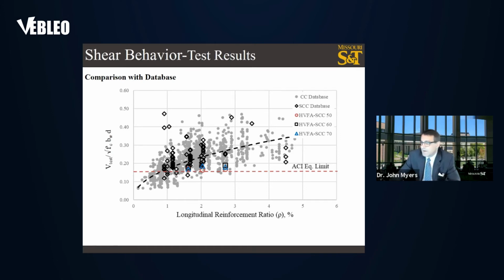Here you can see the experimental data of the different high volume fly ash values, other SCC databases without the high volume fly ash in them, as well as the conventional concrete results. You can see that our test results are generally on the lower side of the band of test data, which may warrant the consideration eventually, as more data is obtained, of a correction factor for this type of concrete. But it does exceed the current minimum ACI equation limit.